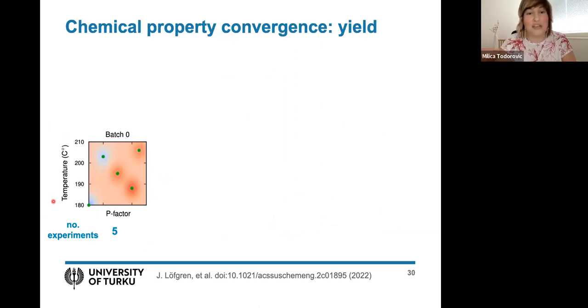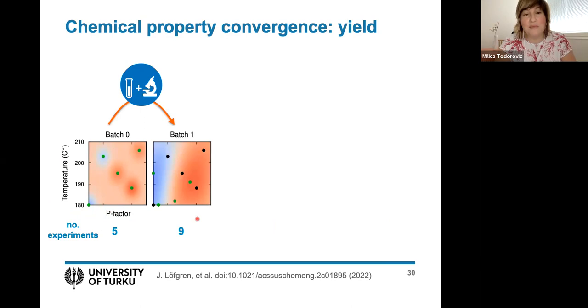So here's the initial batch. We started with five data points. And what you see here is the yield of lignin, so how much lignin was produced in the search space of the P factor of the reaction, which describes severity, and temperature of the reaction. And so when we did a batch of four experiments, we added it to the model.